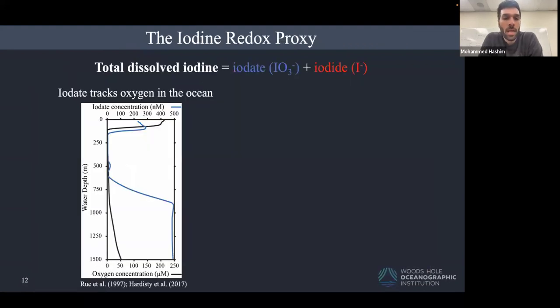So just a little bit about iodine and how it works. There are two main species of iodine in the ocean. One is iodate, which is the oxidized form that only exists when oxygen exists, and the other species is iodide, and that is the reduced form. And what you see here are profiles of oxygen and iodine. And the idea here is that, at least in the surface ocean, iodine and oxygen track each other. So when there is oxygen, there is iodate, and when there is no oxygen, there is no iodate. And again, here we're only talking about iodate in this picture.